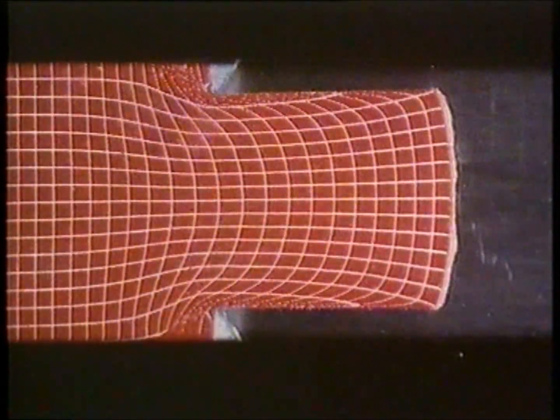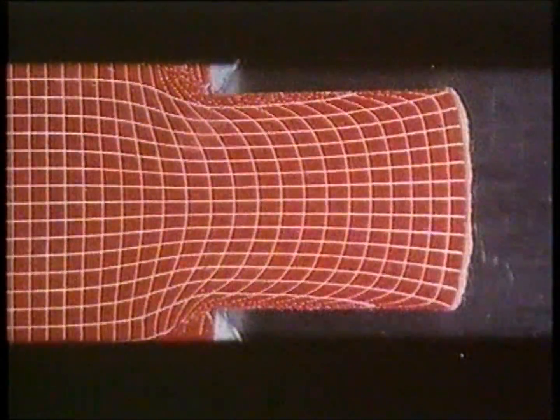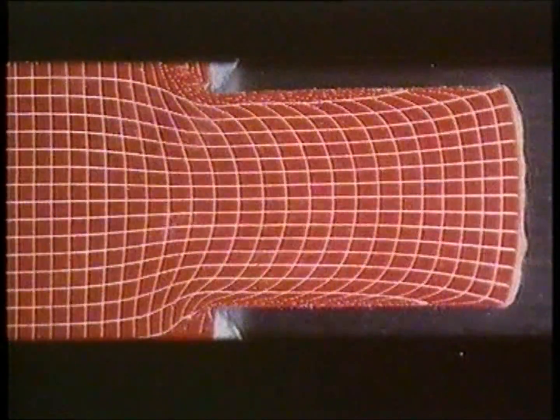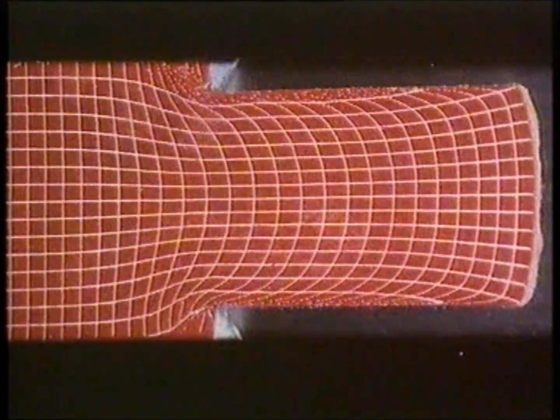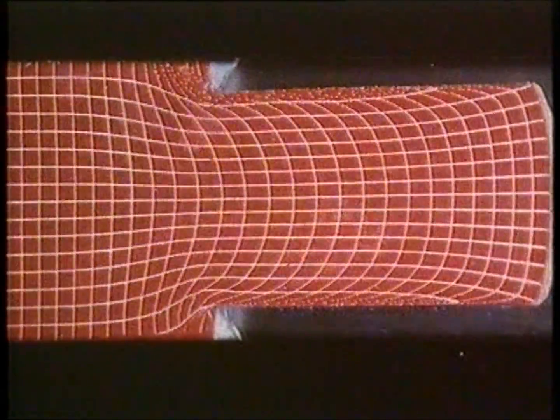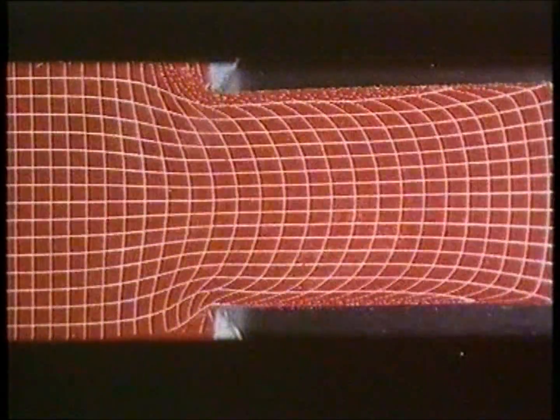Eventually, the material flow causes this zone to be covered with a layer of lubricant. As a result, the deformation near the edges of the extruded material is high in the beginning, but it becomes very low after some time when the dead zones have developed.